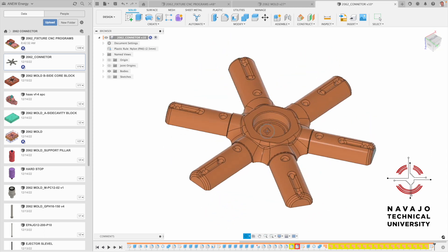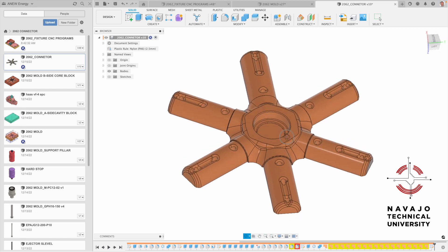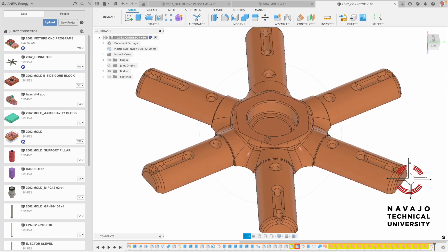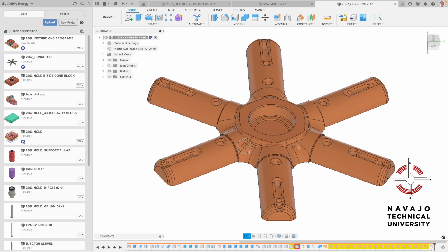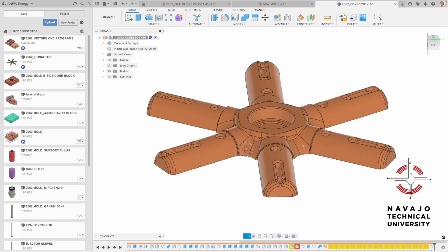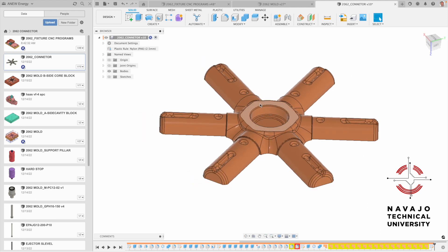We scale the part up a percentage for shrinkage — nylon shrinks at about 15 thousandths per inch, which is about three or four human hairs. From this part we can get the weight to know how big a molding machine we need. This is basic 3D part design for moldability — whether plastic, metal injection molding, or other materials, they all follow the same rules.